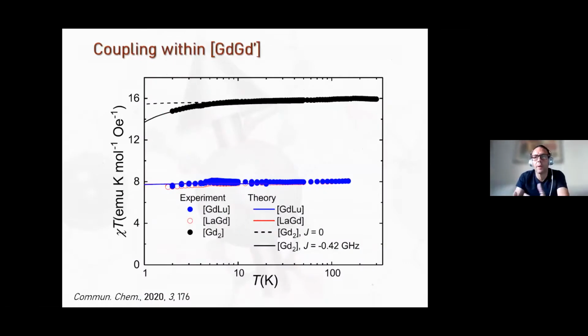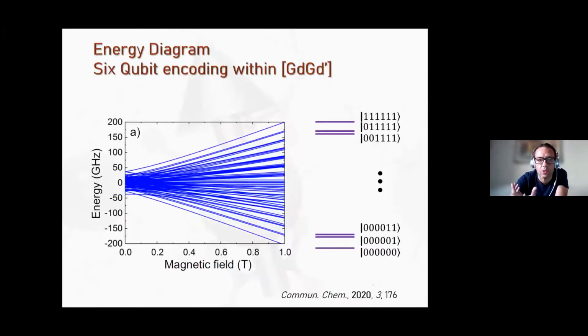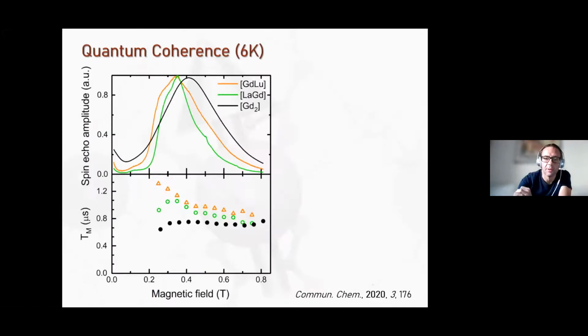We could also compare the magnetic response, the magnetic susceptibility, of these two individual ions compared to the case where both gadoliniums are present, where this weak antiferromagnetic interaction is identified and quantified. So with all this information, we were able to generate an approximate energy diagram that would engender these 64 states, which are the computational basis of a 6-qubit system, with the only problem that there is some crowding that somehow makes it difficult to address every single state individually.